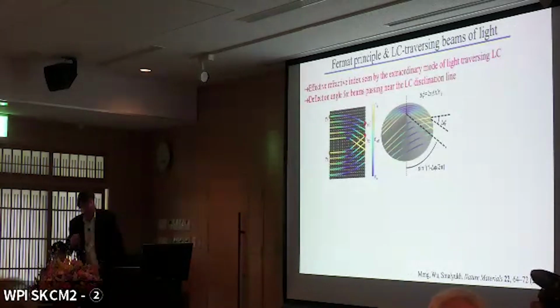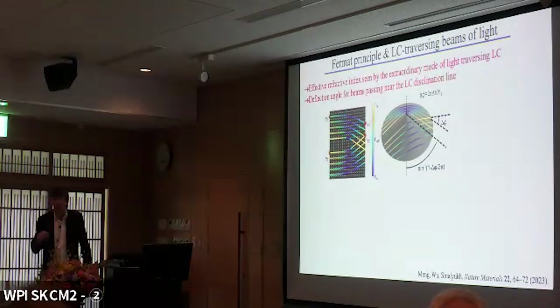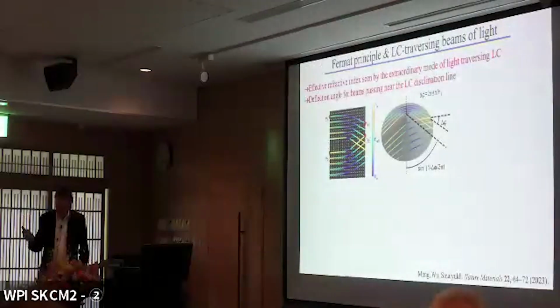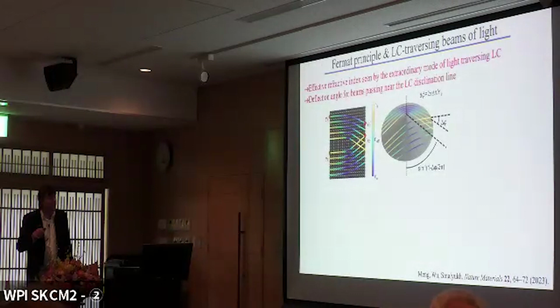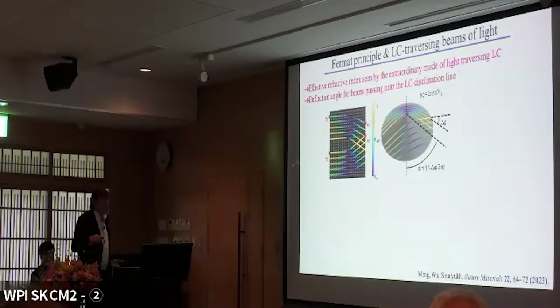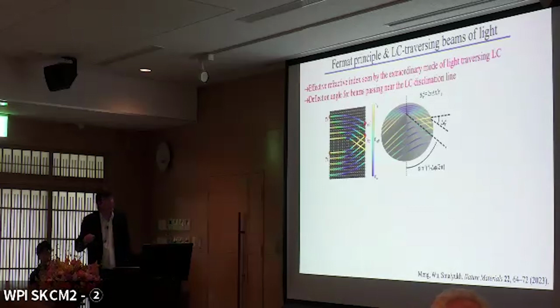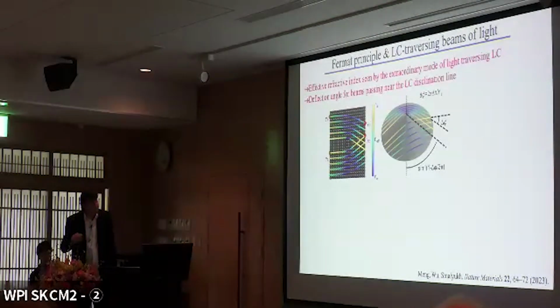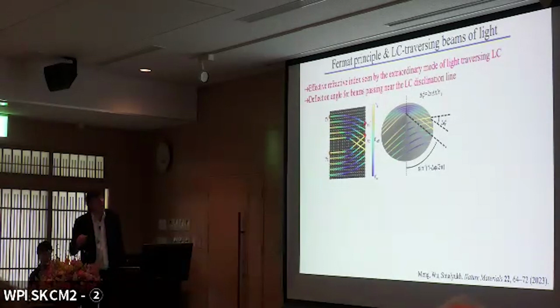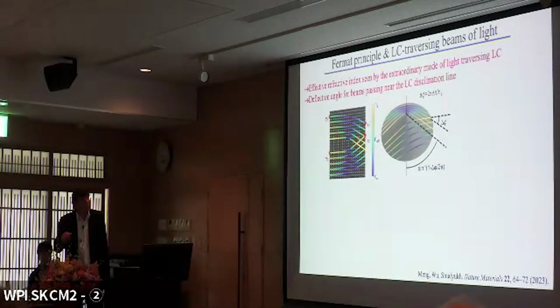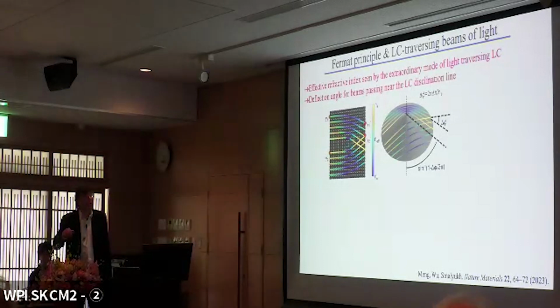And in the first part, I would like to show how liquid crystal vortices can be used to steer light and also to localize light spatially. So in a liquid crystal medium, a polarized beam of laser light will experience an effective refractive index. So if we have an extraordinary mode of light propagating within a liquid crystal, and we have such a vortex